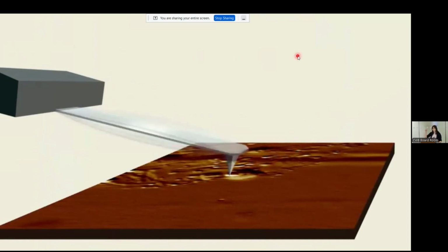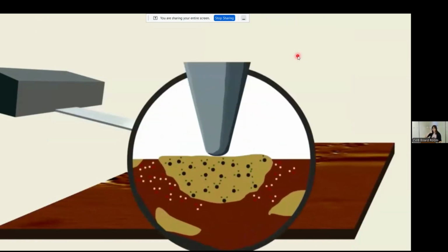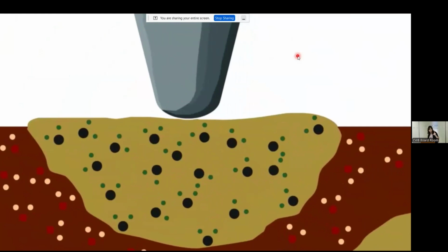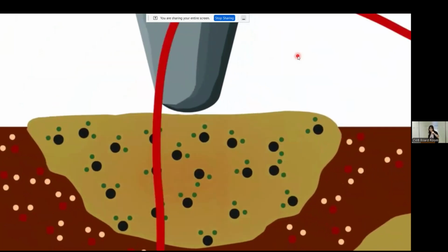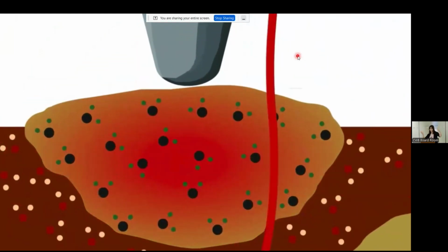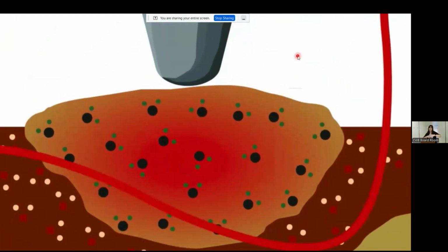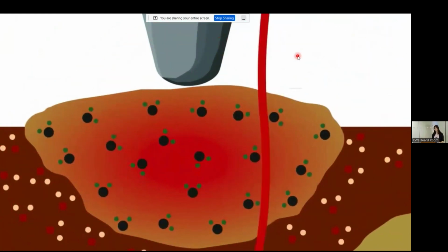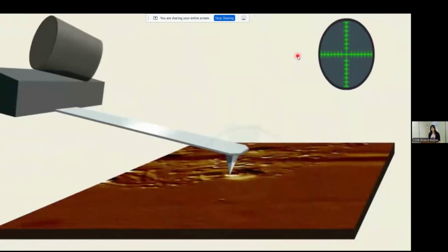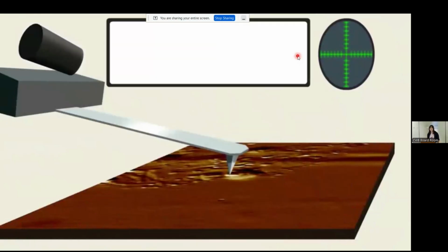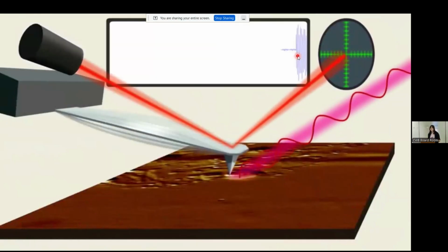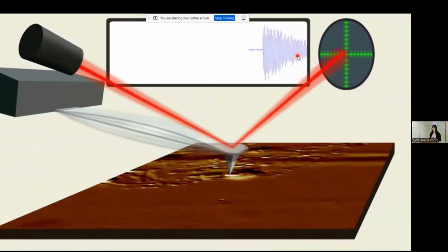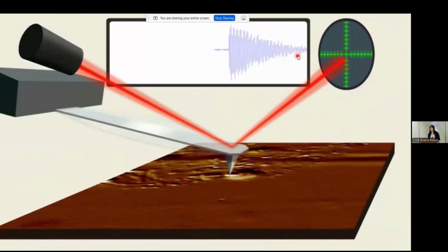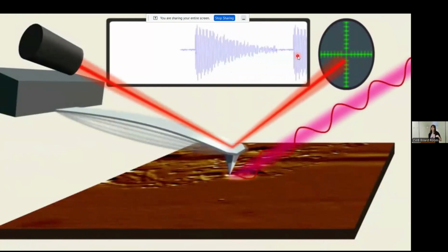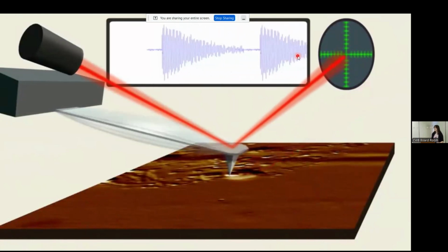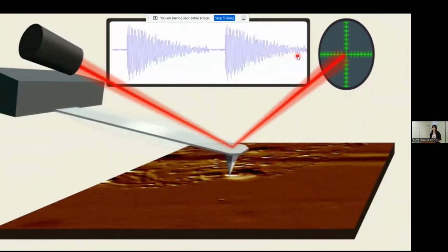So because we have that laser that detects the position of the AFM cantilever, I guess we'll first look at what's happening when things are heating up. You can see that they're expanding outward and they're pushing back on this AFM cantilever. And now, using the AFM itself, we're just detecting the wobble. And so by measuring that magnitude of that wobble, you end up getting the infrared response in this material.